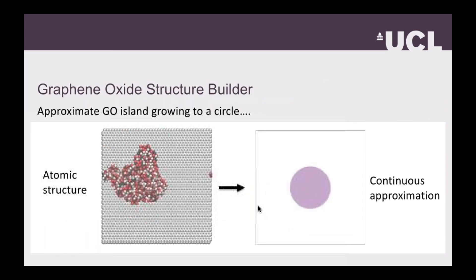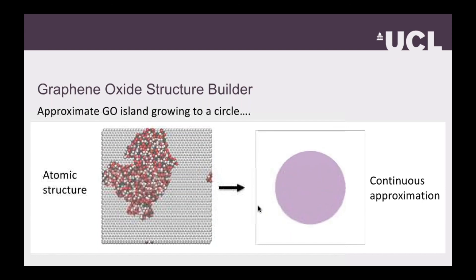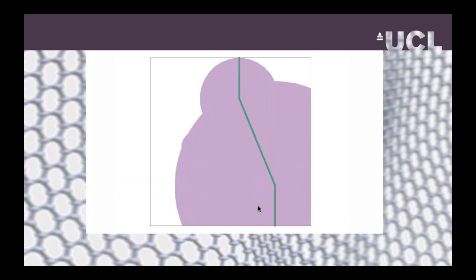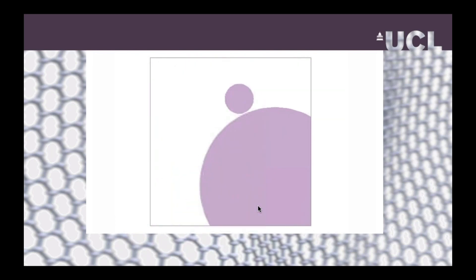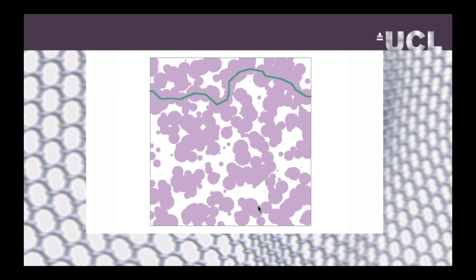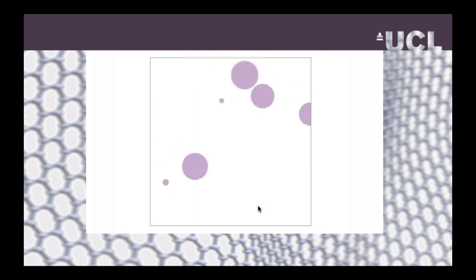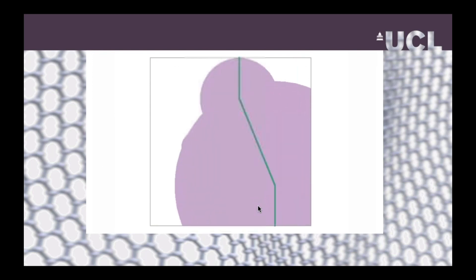Next, we wanted to see that if you've got a two-phase evolving region, you'd be very interested in its percolation threshold. If we model a growing oxidized domain as a growing circle, we have a two-phase system and can study how it evolves over time much more efficiently — this is a kind of surrogate model. I'm stopping each of these animations when the percolation threshold is reached. The reason we're interested in this is because once the oxidized regions shown in pink are percolating, you can expect graphene oxide properties to significantly fall off — things like mechanical strength, conductive properties, and semiconductor properties will change drastically.